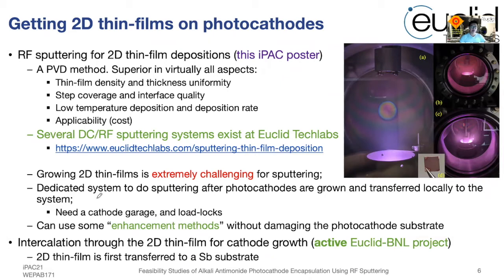Then the next question is how to get the 2D thin films on the photocathodes. There are several approaches to get the thin film deposited on the photocathode. For this IPAC poster, we are talking about the RF sputtering approach. There is another approach that we are actively working on, a procedure where we first transfer the 2D thin film onto the antimony substrate, and then we grow the photocathode through a cesium intercalation. This is, again, being done by a collaboration between Euclid and BNL.